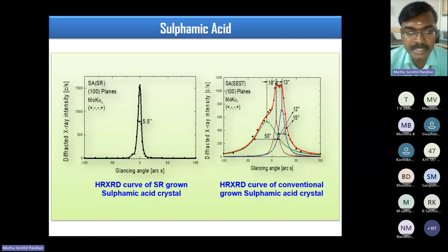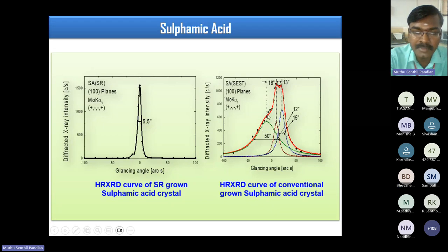To check the crystalline perfection, we performed the HR X-ray measurement. This is for the sulfamic acid single crystal, and a lot of low angle grain boundaries appear for the conventional method grown crystal. The entrapment of solvent molecules into the crystalline matrix is responsible for these low angle grain boundaries in the conventional method grown crystal. But in the case of the SR method grown sulfamic acid single crystal, the full width at half maximum is 5.5 arc seconds, with a single and very sharp peak, which clearly indicates that the crystalline perfection of the SR grown crystal is superior to the conventional method grown crystal.